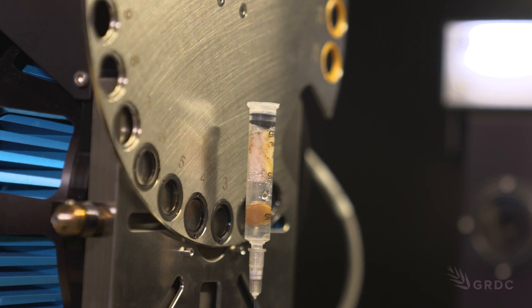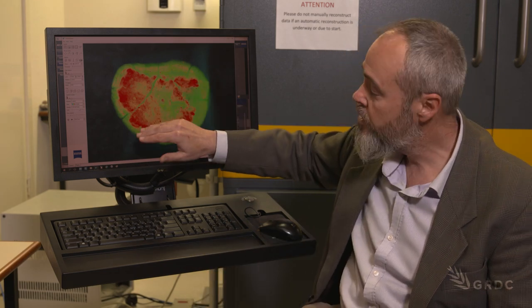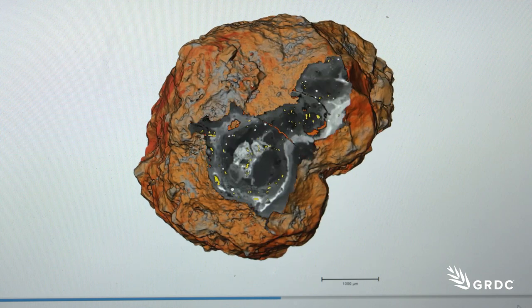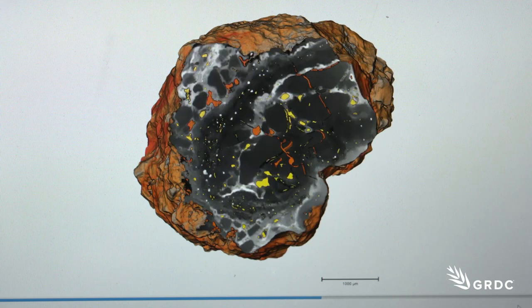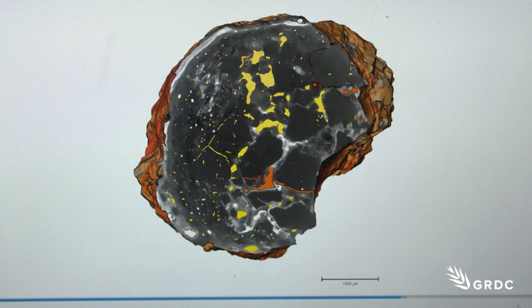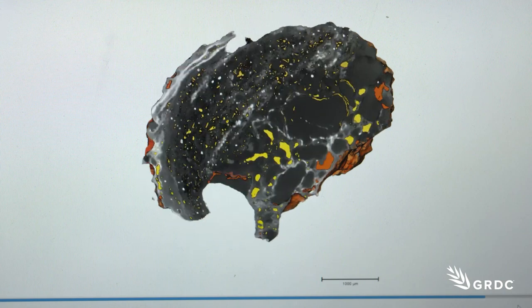Where we've advanced from last year is to use special sample processing techniques where we're using a dye to penetrate into the sample, and that shows us clearly where the water moves into the gravel. As we slice through the gravel, the orange regions represent where water can penetrate into the gravel, whereas the yellow areas are pores that are not accessible to water.